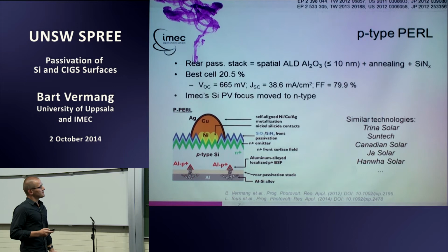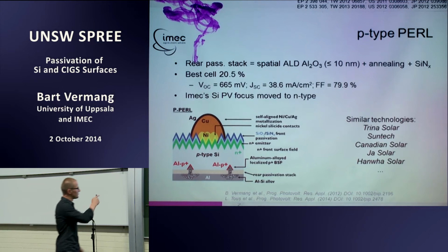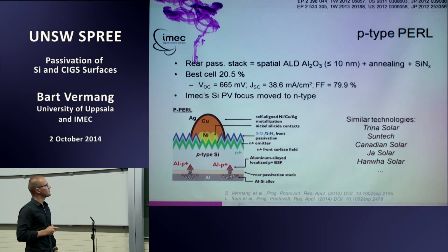So what we did is we are using spatial ALD aluminum oxide, a thin layer like I said, typically less than 10 nanometer. We do anneal it, and we use then a silicon nitride layer on top of it to have more reflection from the rear side. So rear internal reflection. In the meanwhile, at IMEC, best large area cells are typically around 20.5%. Decent VOC, JSC, and fill factor.